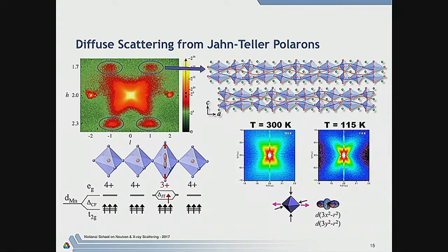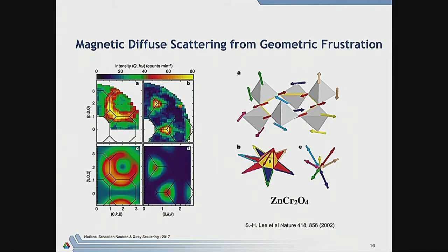Our postdoc, Brandon Campbell, was able to produce a beautiful model of just what the polaronic correlations are. They have a tendency to form these kind of stripes in the orthogonal plane. Okay, so CMR, colossal magnetoresistance, is one of the consequences of this polaronic disorder. And it was a hot topic at least 10 years ago and is still studied now.